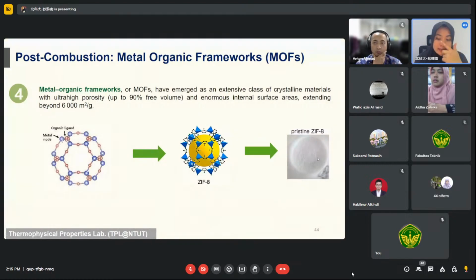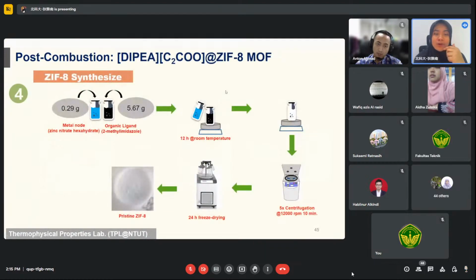One of the most common is ZIF, or zeolitic imidazolate frameworks, code 8, because they have many types like 8, 67, and so on. So we choose 8 here because it's practically good for CO2 capture. It looks like this for the synthesized ZIF8. Then how is the process? In this case, I don't use just ZIF8. I will encapsulate it with the ionic liquids, the good one that we measured previously, to increase the CO2 capability.